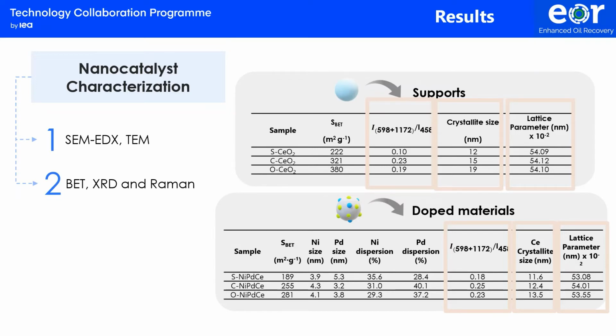Also, for the doped materials, it was observed that the lattice parameter is reduced relative to the non-doped systems. This reduction can be attributed to a portion of nickel and palladium ions substituting the cerium 4+ in the ceria lattice and altering the unit cell parameter of the support, since a relatively smaller radius is found for nickel 2+ and palladium 2+ than cerium 4+.